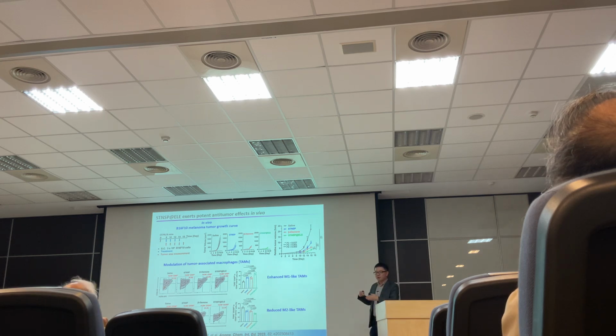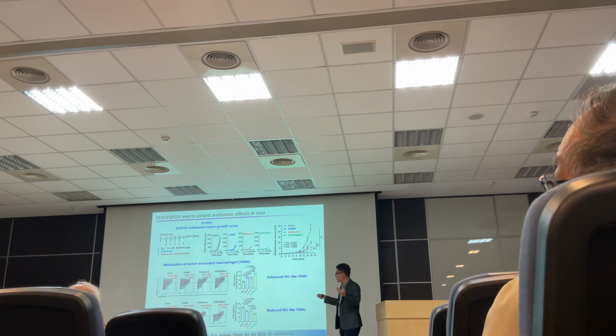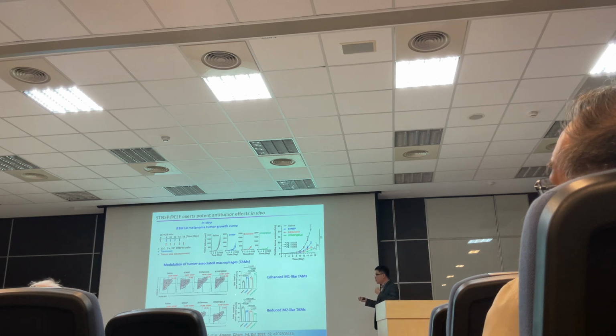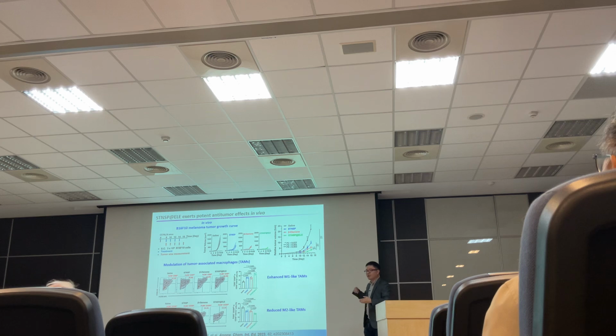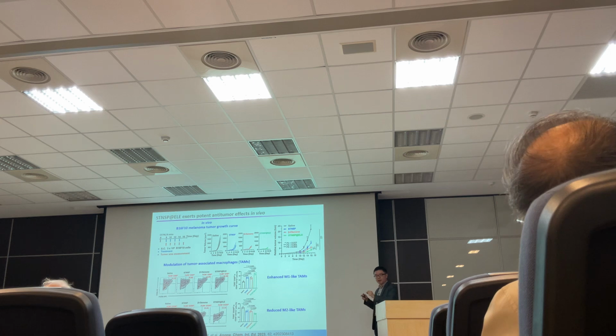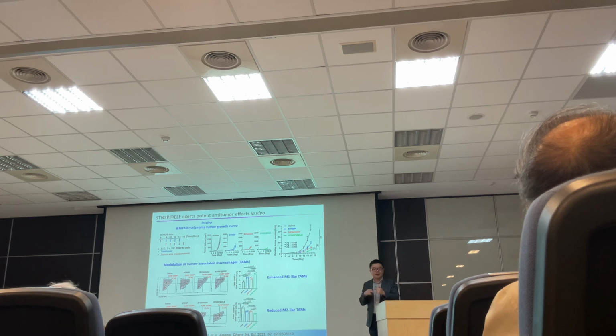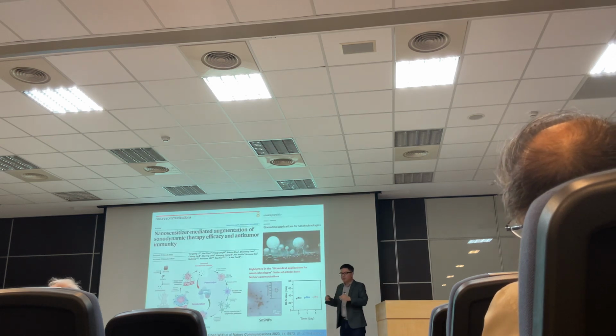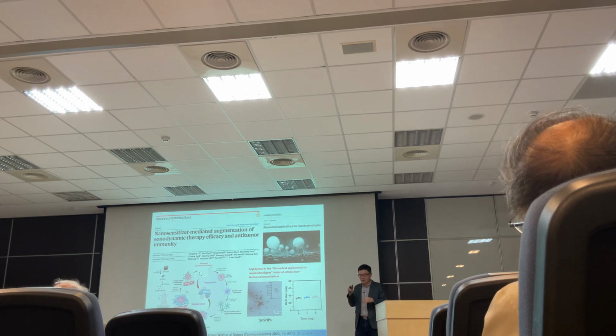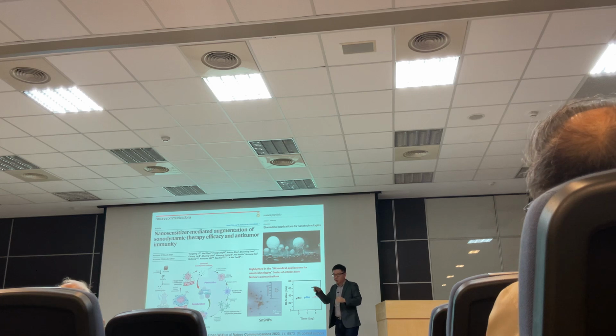We also harvested the residual tumors and then analyzed the population of the immune cells, like M1-like and M2-like macrophages. And surprisingly, to our surprise, in the tumor model we also discovered that the M1-like macrophage increased, and the M2-like, this pro-tumor macrophage, decreased. So this data shows that our materials can modulate the tumor microenvironment and the macrophage population to achieve chemoimmunotherapy. And as I mentioned, in the tumor microenvironment it's not only about the tumor cells, not only about the macrophage, but also about the whole tumor microenvironment.